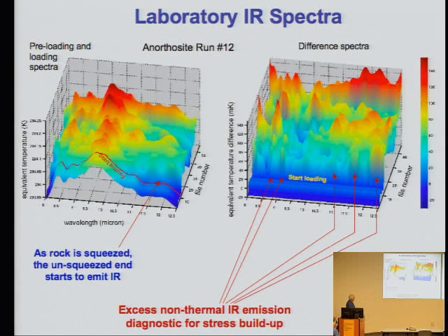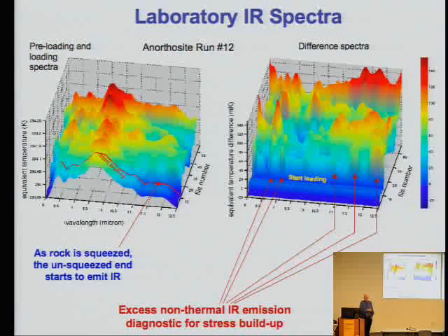So, we see a spectroscopic signature that is characteristic of a process consistent with what we have known through the other laboratory experiments from the behavior of the rock, the recombination of positive hole charge carriers, and the first layer of these would emit electrically or vibrationally stimulated. So this is not temperature. It's like an LED. It's a non-thermal emission process, stimulated emission, controlled by the quantum transition between vibrational excited states.